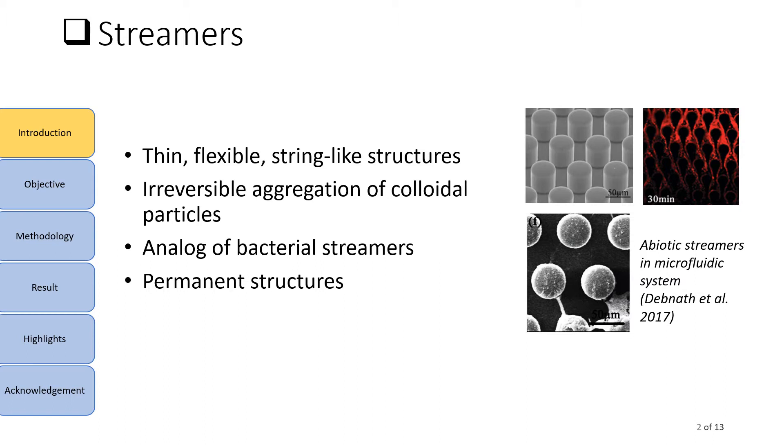Streamers are thin, slender, string-like flexible structures formed by irreversible aggregation of colloidal particles. This colloidal streamer was first reported by Debnath and co-authors. They found that when particle laden polymeric fluid is allowed to flow in a suitable microchannel, particles aggregate in form of thin string-like flexible structures with one end tethered at micro pillar walls and the other end floating in the background flow.